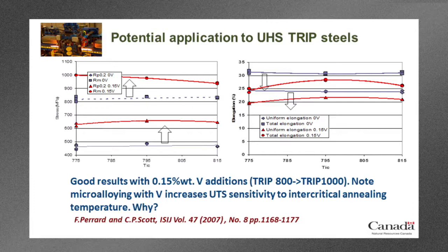Now the blue points are the reference points with no vanadium, and the red curves are the curves that we obtained once we'd added 0.15 weight% vanadium. You can see that at certain intermediate temperatures, intercritical temperatures, excuse me, we have a gain of almost 200 megapascals in the ultimate tensile strength. And that is an extremely useful property that vanadium could give these steels.